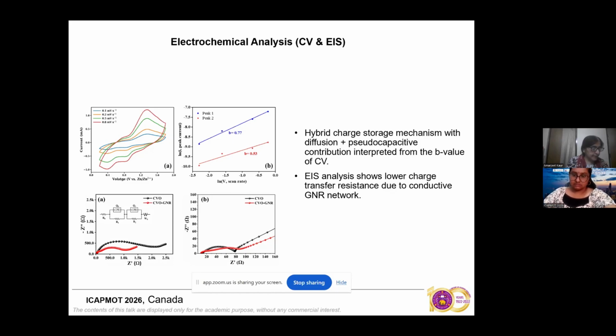So what we can infer from here is that, generally, if we plot the peak current versus the scan rate, then we get the slope. It is a straight line given by i = a v to the power b, and the values of this b are 0.53 and 0.77. When the b values range between 0.5 and 1, it represents a hybrid storage mechanism. That is, it has both the diffusion current and the capacitive current also there.